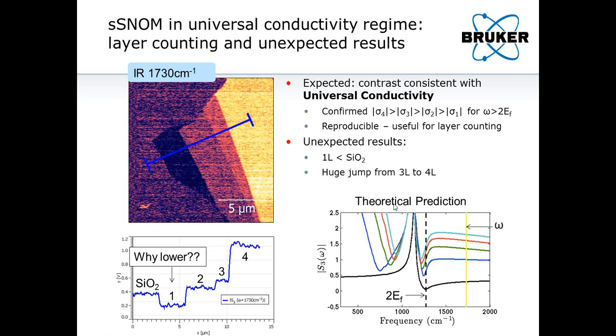And I made a theoretical prediction. I calculated the expected spectrum, and I indicate the frequency that we used to perform our measurement. And as you see from the theoretical prediction, the 1-layer signal should have been higher than the SiO2, and the transition from the 3-layer to the 4-layer should have also been basically in line with the other transitions.